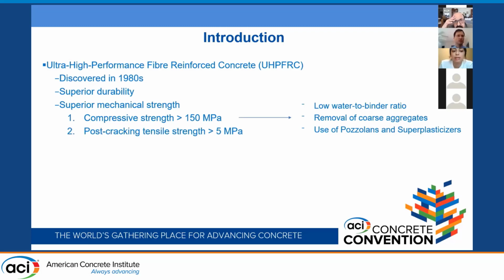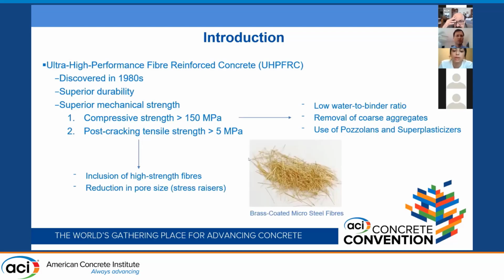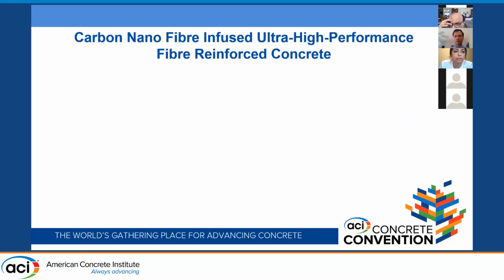The second is that it has a post-cracking tensile strength that is typically in excess of 5 megapascal. And that is due to the inclusion of high-strength fibers, mostly steel fibers, as you can see here in the picture, and the reduction in the pore sizes, which are stress raisers. So by reducing the pore sizes, we are making the stress more uniform in the matrix, which makes the material stronger.